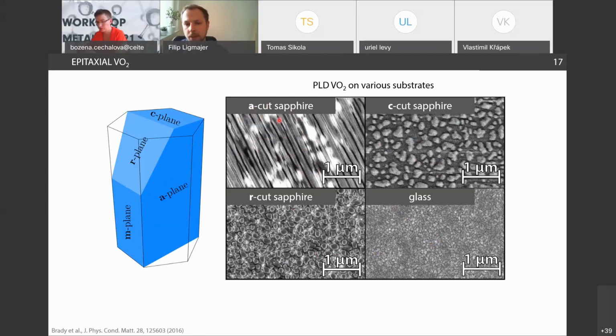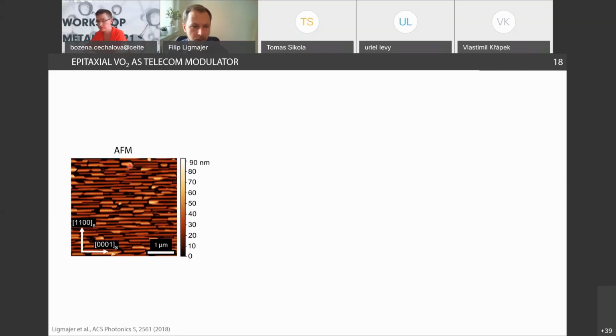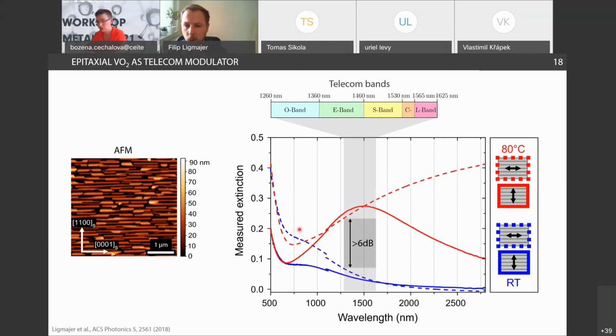And when we realized there is a confinement in these nanobeams, we thought, okay, this might also exhibit plasmonic resonance, because localized plasmonic resonance is always related to some sort of confinement of your material. So we investigated these films a little bit more. We did AFM, we did XRD on them. We studied the orientations and described how the orientation of the sapphire substrate gets translated into the orientation of the nanobeams as well. What is the mechanism behind it? And most importantly, we studied the optical properties of these materials.